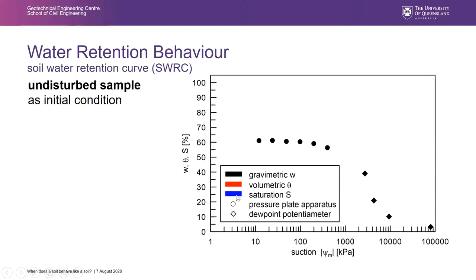And that was done also with tailings, of course. And we started this test with an undisturbed sample. So now this shows you the evolution of the gravimetric water content versus the applied suction. The circular symbols were measured with the pressure plate apparatus, so basically by applying an overpressure in the air phase, and the rhombuses were measured with the dew point potentiometer.